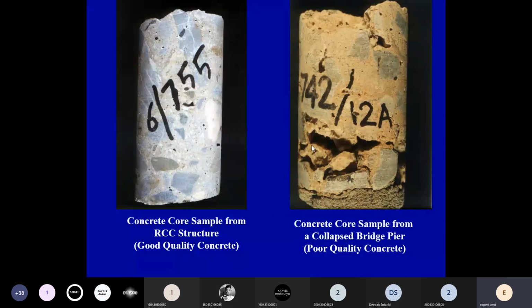And this is how a concrete core sample looks. So again, the visual observation comes into play here. If you see a concrete core sample from an RCC structure of good quality, this is how it looks. It's well compacted, with minimal voids. And if it is from a collapsed bridge pier, which has poor quality concrete, you can see there are voids, there is delamination, separation of the concrete, and also the distribution of aggregate and color of concrete is not appropriate. So it indicates that it's poor quality concrete.